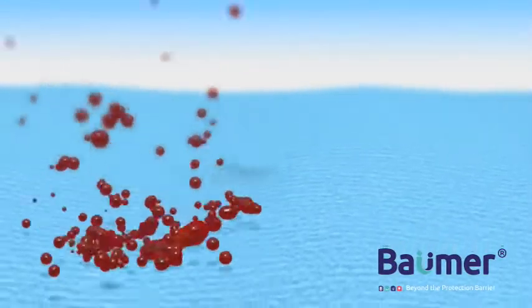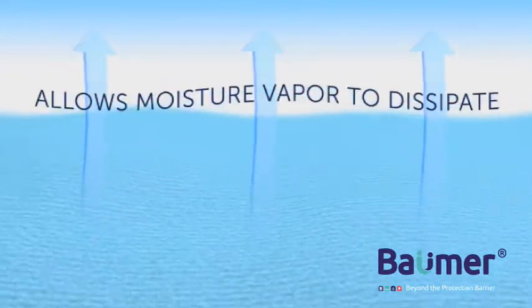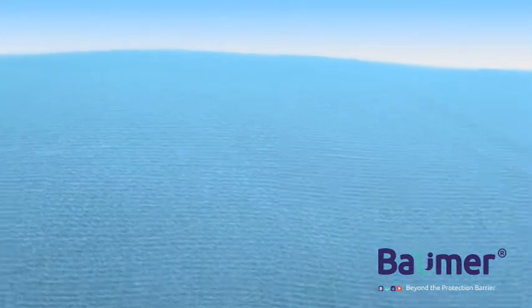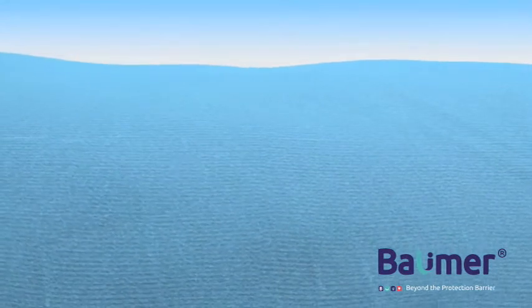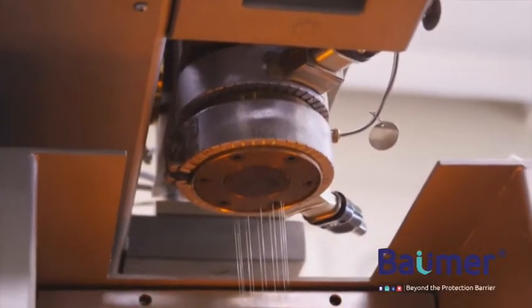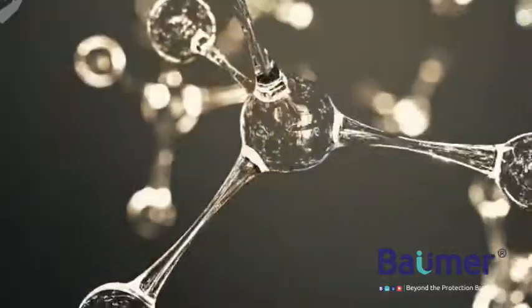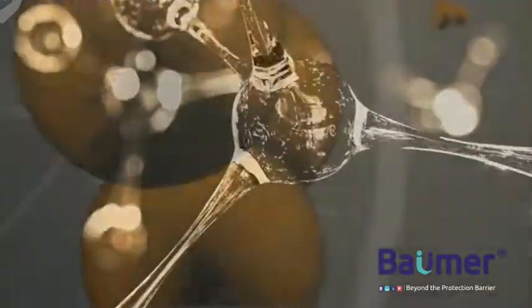In this process, the nanoparticles are distributed and embedded uniformly throughout the volume of each of the fibers, providing a highly durable effect. Our combined filament extrusion line gives us the possibility of incorporating nanoparticles into polymers, spreading properly and efficiently, in such a way that we can manufacture the fibers without breaking them.